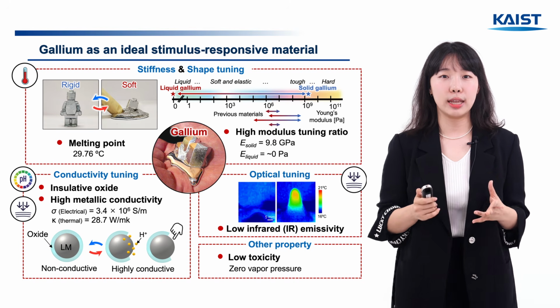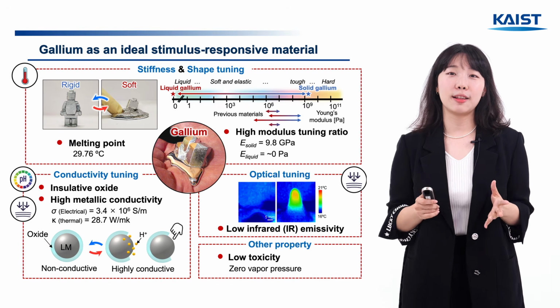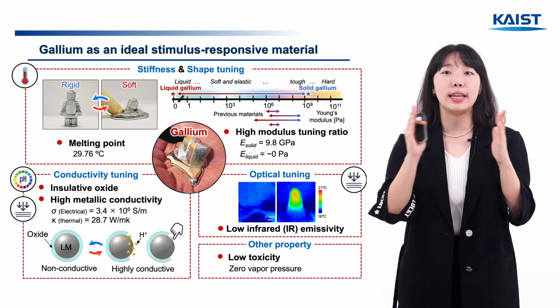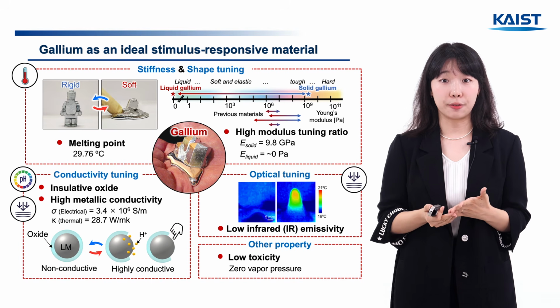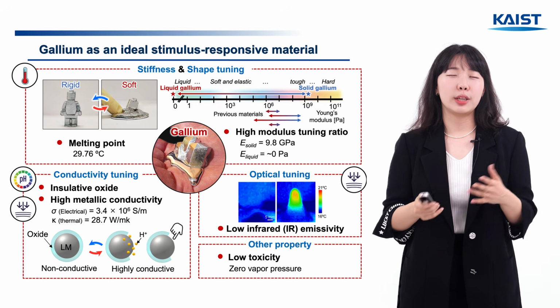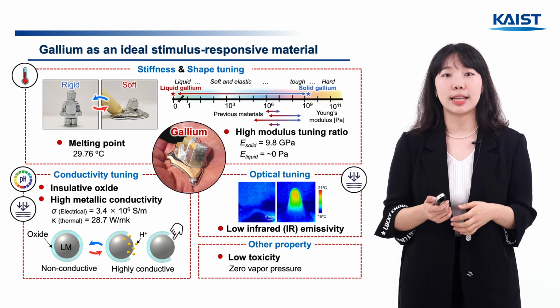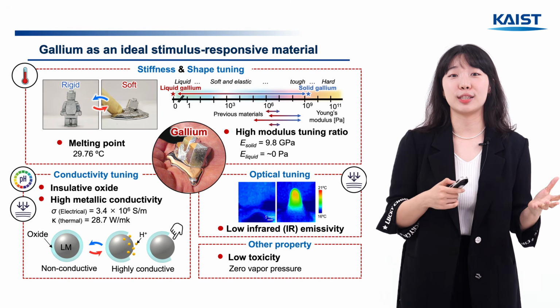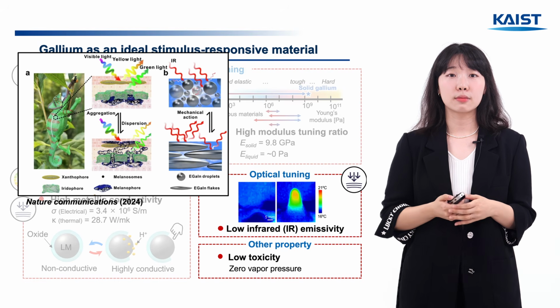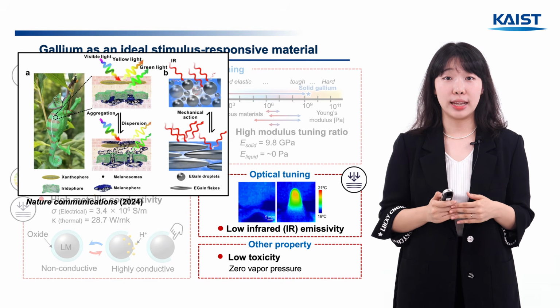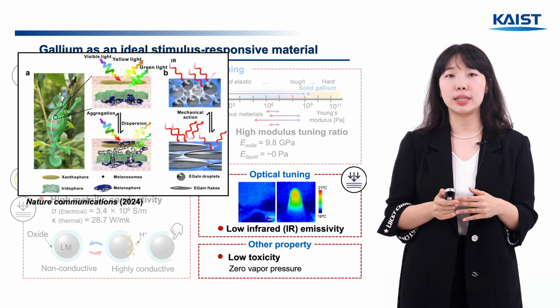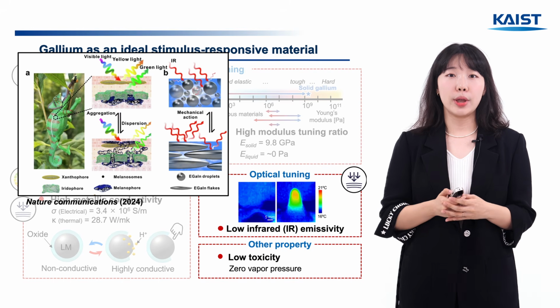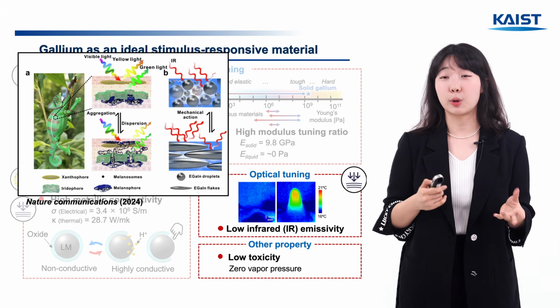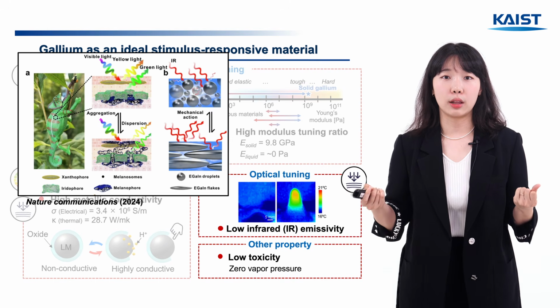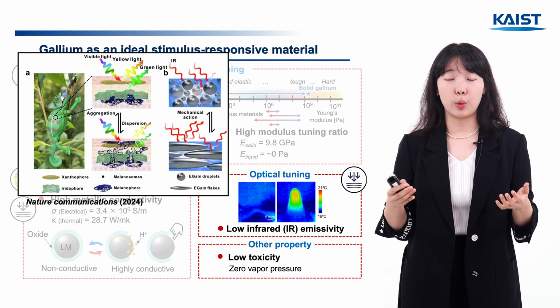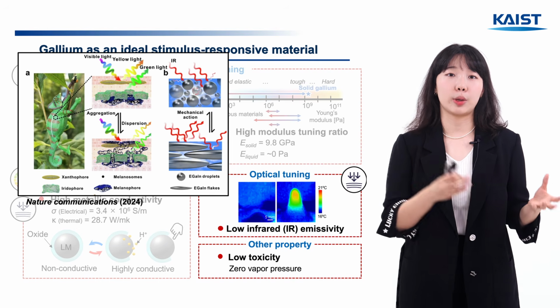In terms of conductivity, it's also interesting because gallium itself is a metallic conductor, but an insulating oxide layer forms naturally on its surface. You can remove that layer with acid or by applying pressure, which lets you switch its conductivity on and off. It also has low emissivity, which means temperature changes cannot be detected in the infrared range. But when you mix it with a high emissivity material, for example PDMS, stretching the liquid metal lets you tune how much temperature change shows in the infrared, depending on the location of the liquid metal.